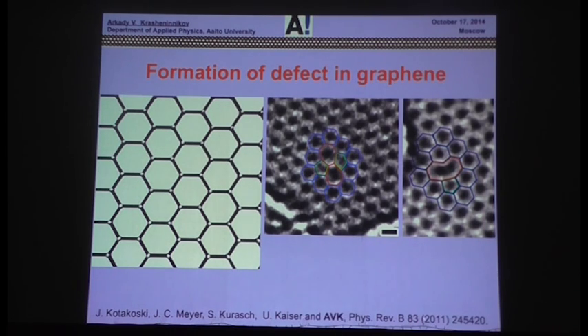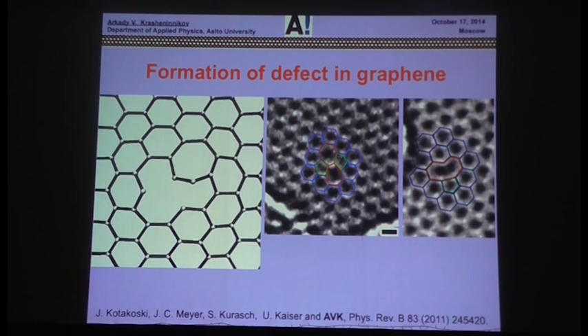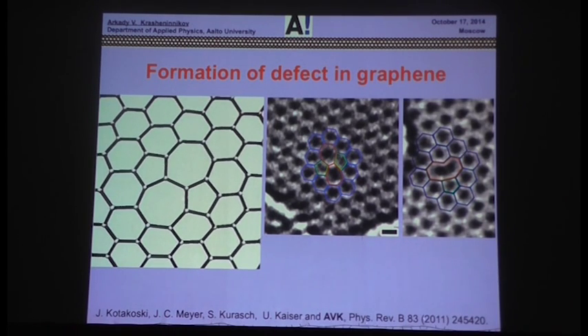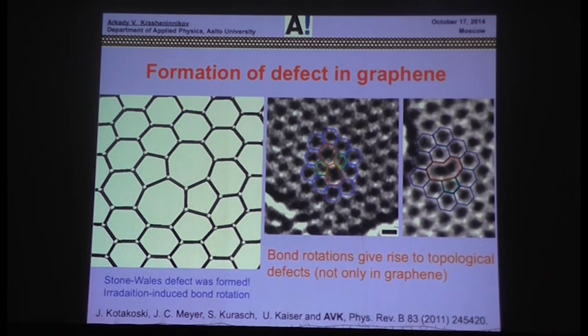The electron comes from below once more. It's a movie. These are experiments, of course, with two images. And you see that the atom was almost displaced, but it came back, and you get two heptagons and two pentagons. So essentially, the important issue here is that the electron beam can rotate the atom and give rise to topological defects. Basically, no atom is missing in the Stone-Wales defect, but the local topology is different.